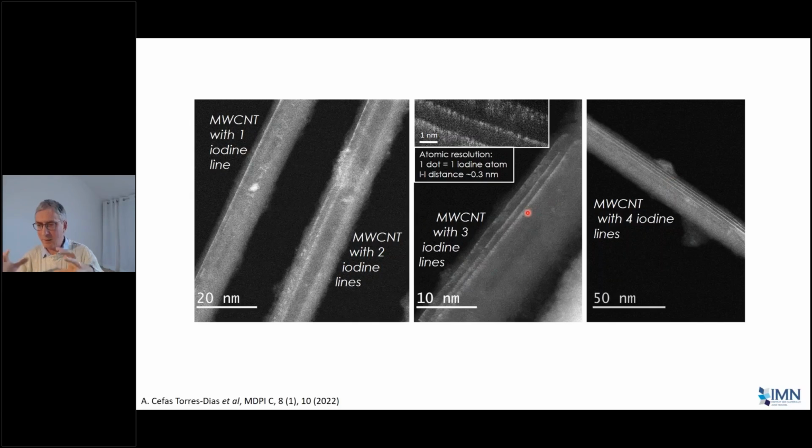Because the layers are buckled, there's just enough space for iodine atoms to fit in there, just one at a time in a row. And they're very stable there because they transfer charge to the surrounding sheet, so they sort of sit in a little cocoon of charged carbon. So you make little cavities that you can fill.